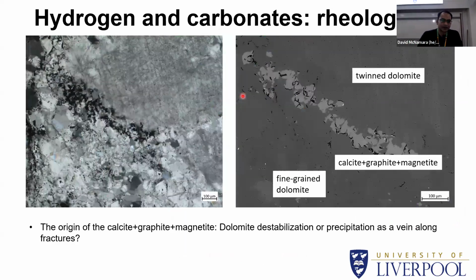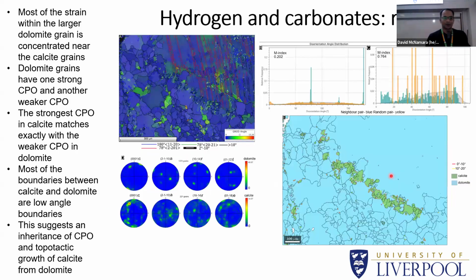Now, the second bit is calcite growing onto dolomite from dolomite, or just precipitated by an infiltrating fluid. First thing is we always see this common assemblage that's calcite, graphite, and magnetite. It's never calcite by itself, and the importance of this will be stressed later on. But first, if I were to show you the EBSD map of this domain, then we've got a lot of twin dolomite here, the finer grained dolomite here. But the important thing is if we look at the crystallographic preferred orientations of dolomite and calcite and this pit that I've highlighted in red, this is the CPO of dolomite, this is the CPO of calcite.